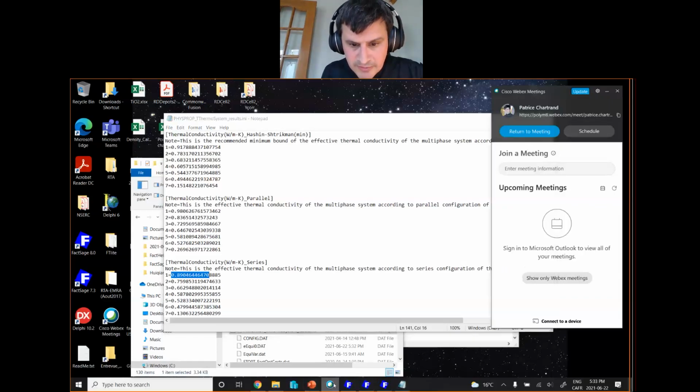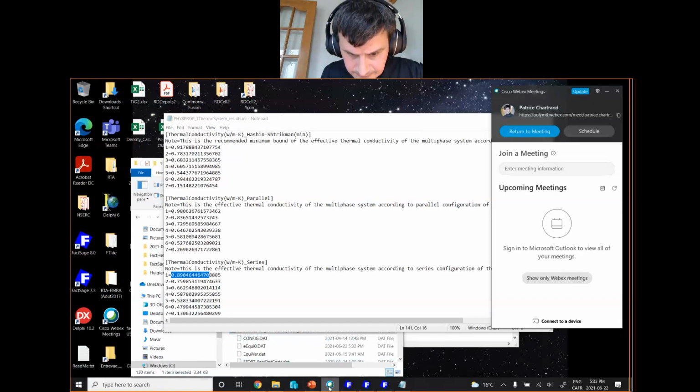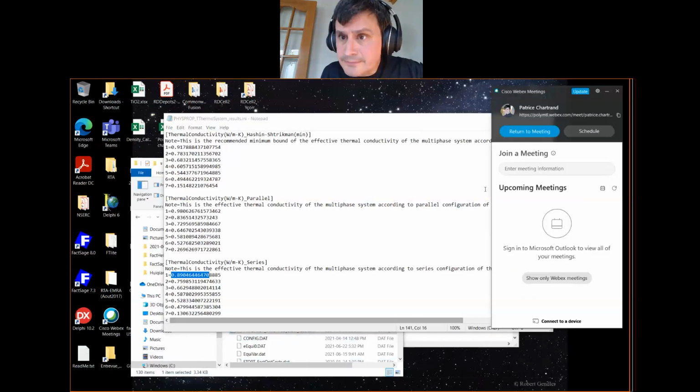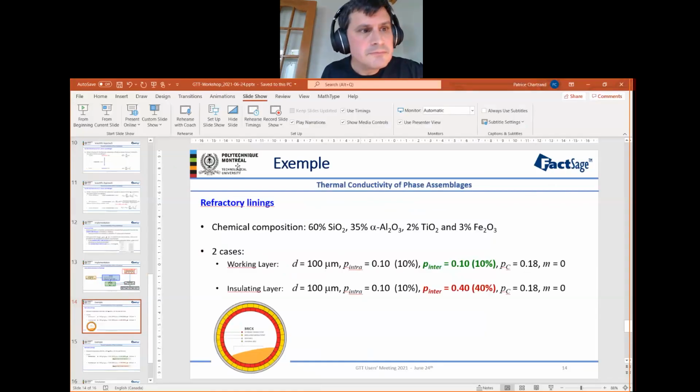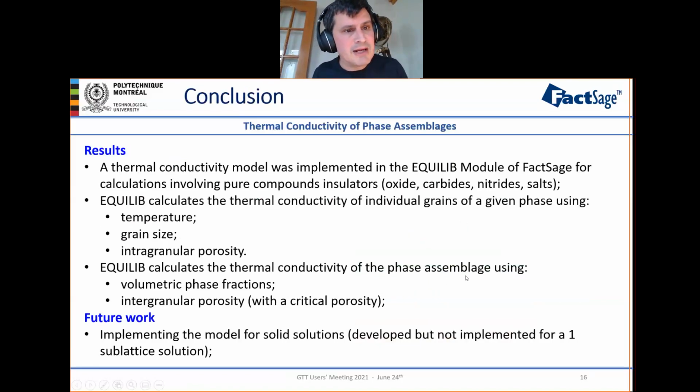I go back to my presentation. And as you can see, there is a very big difference in the thermal conductivity with the same phase assemblage except for the porosity, going from 10 to 40%. So as a conclusion,